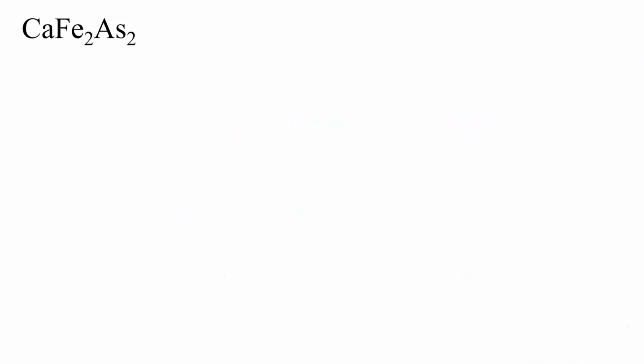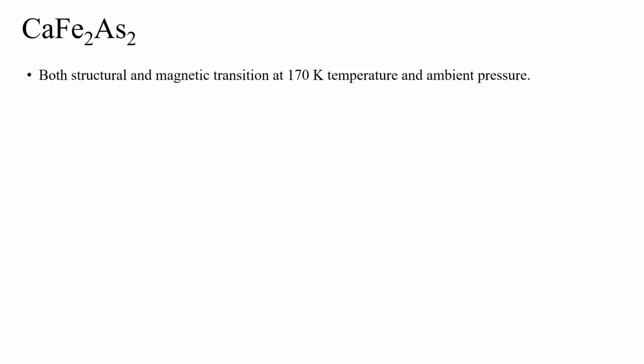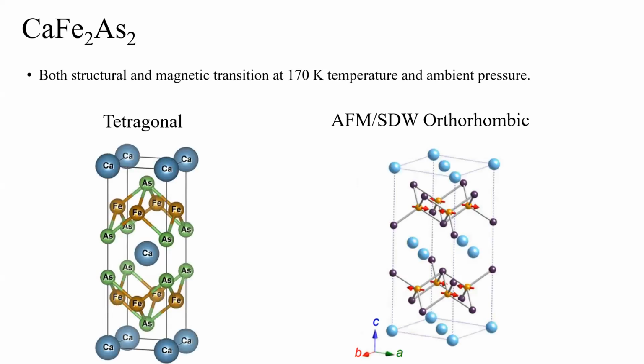Since all these iron-based superconductors share similar properties, we basically looked at the CaFe2As2 compound, the 122 type iron-based superconductors, the parent compound of iron-based superconductors. It has both a structural and magnetic transition, as I discussed in the first two slides. It shows this transition at 170 Kelvin at ambient pressure, going from the tetragonal to the orthorhombic phase. We have these iron arsenic quasi 2D layers. When it goes to this phase, the local moments at the iron sites are aligned in an antiferromagnetic arrangement.